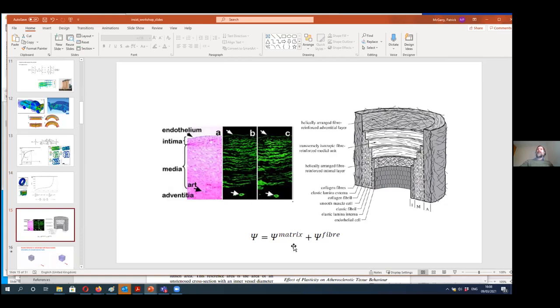And the strategy usually for modeling arteries is to decompose the deformation into a matrix part, which is describing an isotropic matrix. In other words, the material between these fibers. And then separately modeling the fibers and adding the two contributions together.